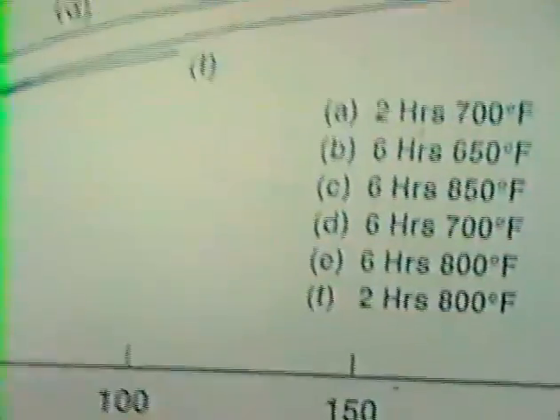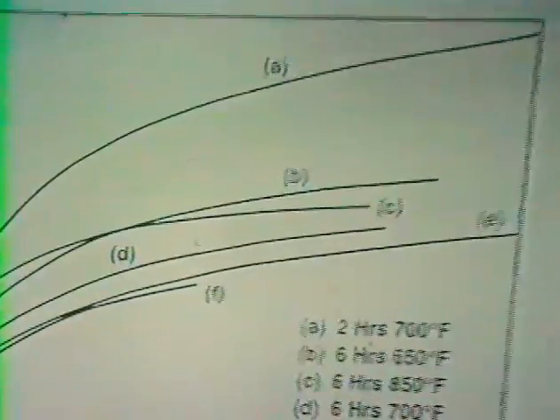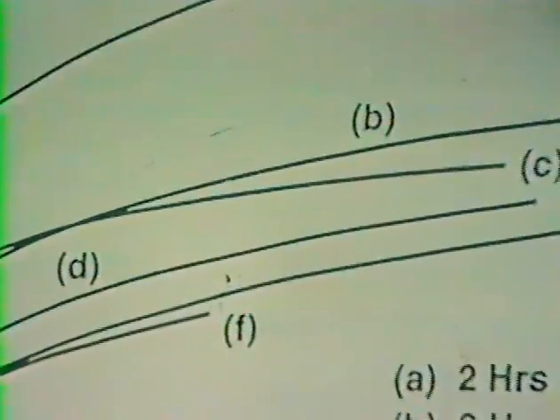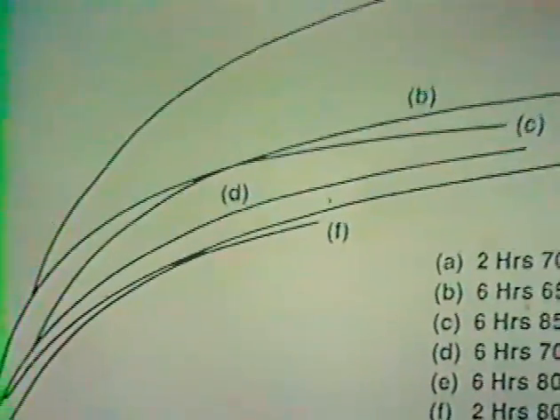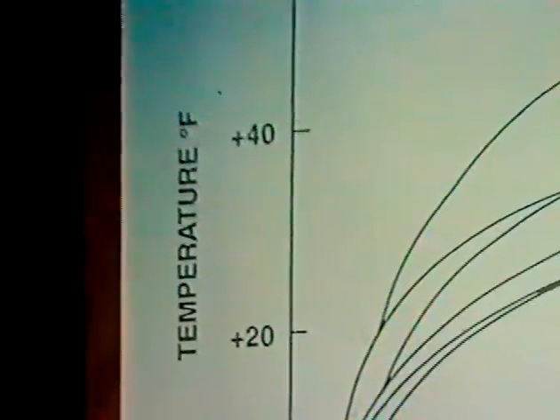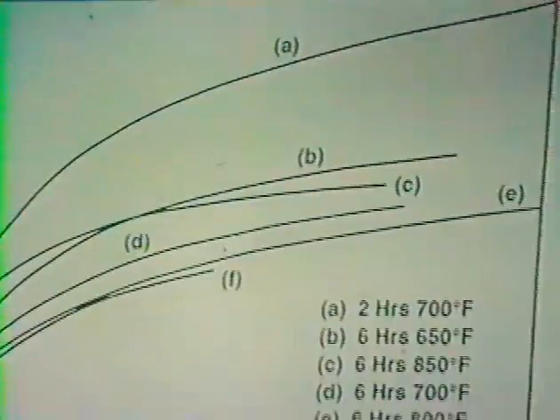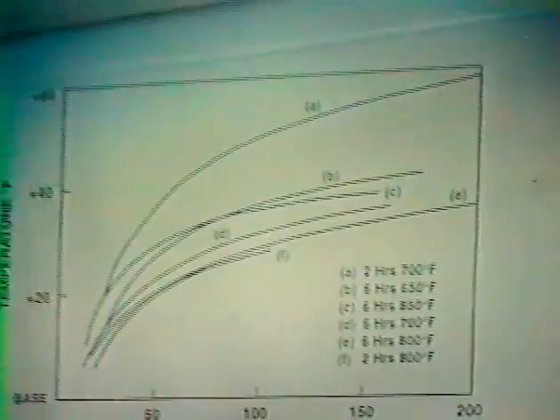In which it is activated in the presence of hydrogen. What we can see in this slide is that how it's activated is critical to its performance. To give you a relative idea, these are measured versus a base point, and each 20-25 degrees change in activity represents a doubling of the activity, or a halving of the activity.